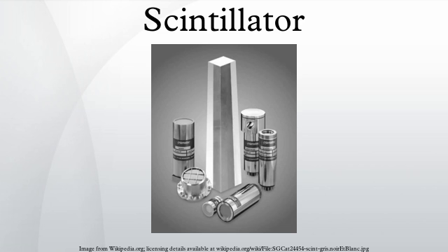Physics of scintillation. Organic scintillators. Transitions made by the free valence electrons of the molecules are responsible for the production of scintillation light in organic crystals. These electrons are associated with the whole molecule rather than any particular atom and occupy the so-called molecular orbitals. The ground state S0 is a singlet state above which are the excited singlet states, the lowest triplet state, and its excited levels. A fine structure corresponding to molecular vibrational modes is associated with each of those electron levels. The energy spacing between electron levels is approximately 1 eV. The spacing between the vibrational levels is about 1/10 of that for electron levels. An incoming particle can excite either an electron level or a vibrational level.